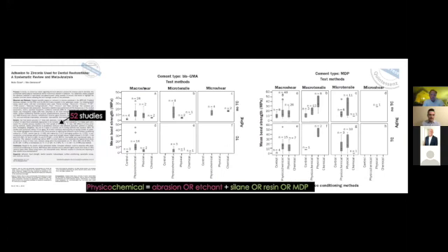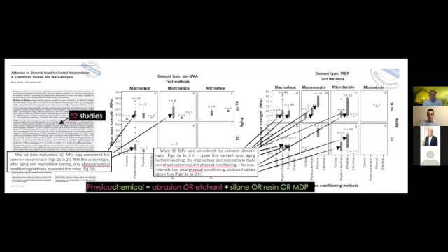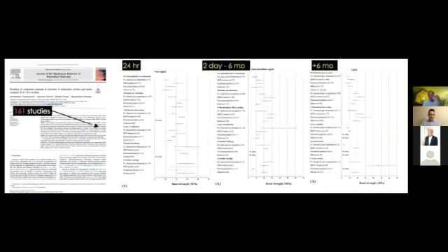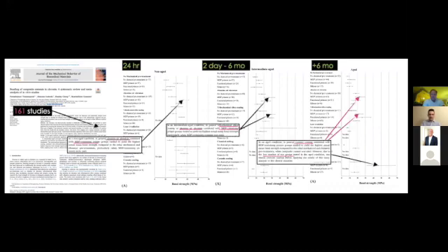This is a systematic review and meta-analysis of 52 studies. One of the neat things in this review is they looked at using a separate MDP primer or using a cement that contained MDP. In both cases, they found that if you sandblasted and then either used a cement which contained MDP or used a separate MDP primer, you get an increased bond to zirconia. And this is just the last one. It looked at 24 hours bond strength, 2 days to 6 months, and then longer-term lab. They found the same kind of deal with sandblasting and application of MDP improving the bond to zirconia.